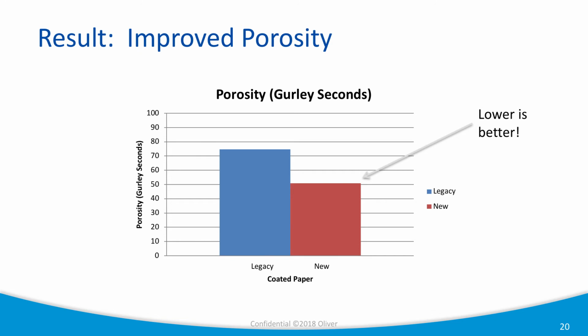We were also able to improve the porosity. And again here, this is higher porosity at a lower Gurley. This is Gurley seconds on the left. The legacy material was around 75, and with the reformulation we're coming in around 50 seconds. So that's an improvement in that way as well. So we had improvements in both areas.